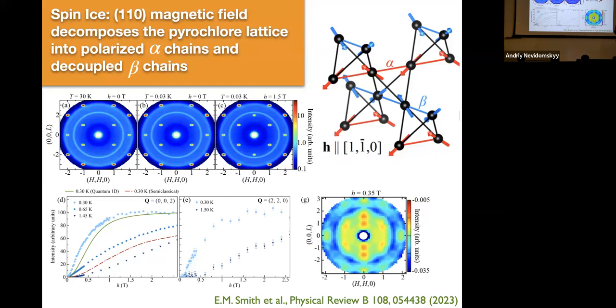You've got these independent beta chains which aren't affected by a field at all, because the moments are perpendicular to the field, so they just stay as disordered one-dimensional chains, and they give rise to this sort of diffuse scattering. It's structured, it's actually quite weak, as expected, but it also comes out of the board, right? It forms a plane of scattering, which is modulated to some extent. You can see the modulations. But there's a plane of scattering that comes out of the board, and that's the signature of these decoupled beta chains. Okay? So this system is behaving in a 110 field as you'd expect a spin ice to behave.